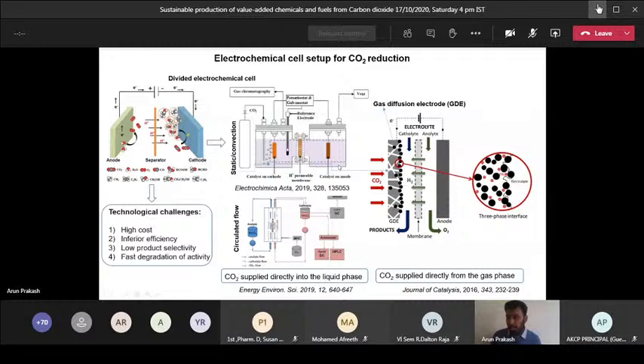As I told, in the case of an aqueous phase electrode, you are feeding the carbon dioxide into the electrolyte, so it cannot dissolve efficiently. When you pass the gas into the electrolyte, it has to dissolve first, diffuse through the electrolyte, and reach the electrode surface. Always diffusion is an issue and solubility is an issue. Whereas in the case of a gas diffusion electrode, you are not purging your CO2 gas into your electrolyte. Instead, you are purging the CO2 gas at the back of your electrode directly. Because of that, there is no need for the gas to pass through the electrolyte, and it can directly feed to the catalyst surface, and by applying the potential, it can react, reduce, and form the product.